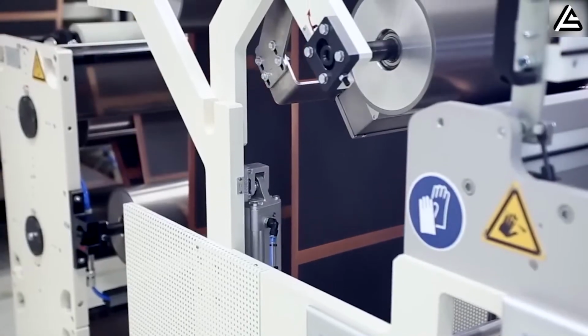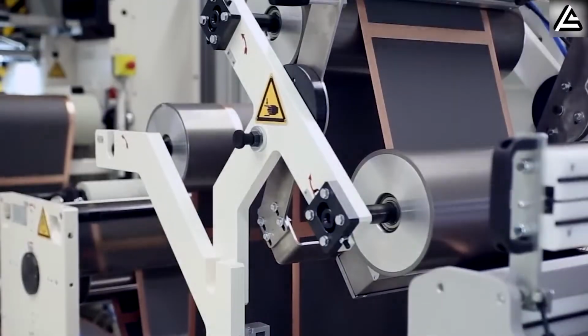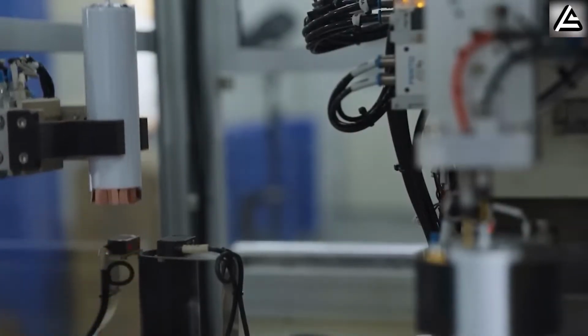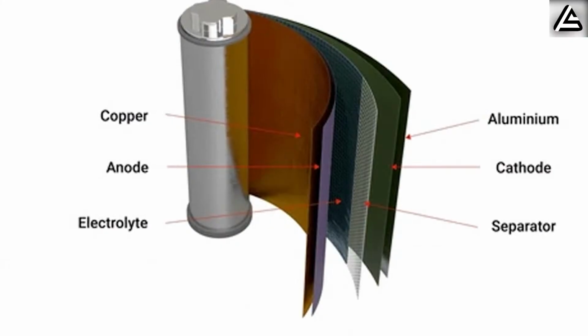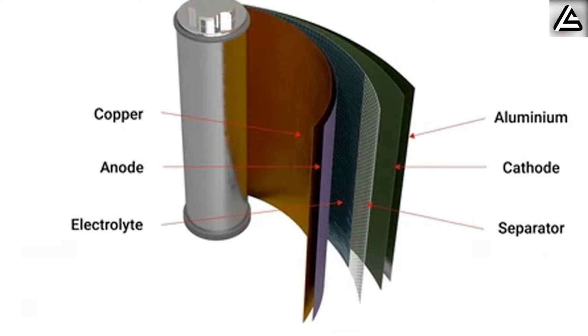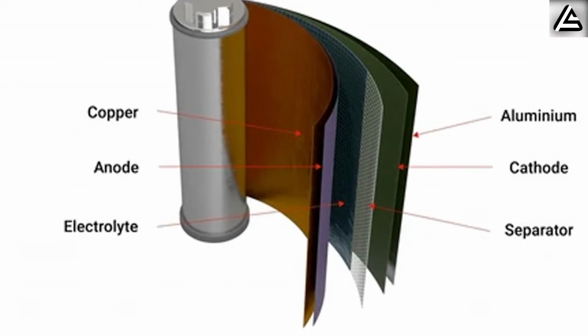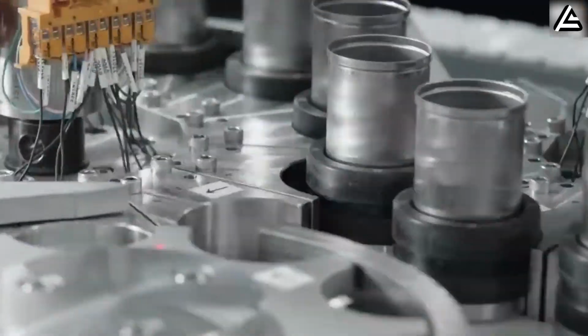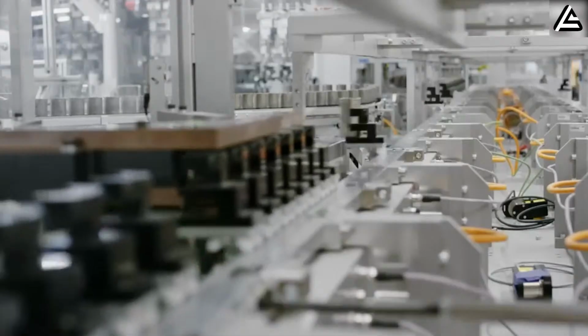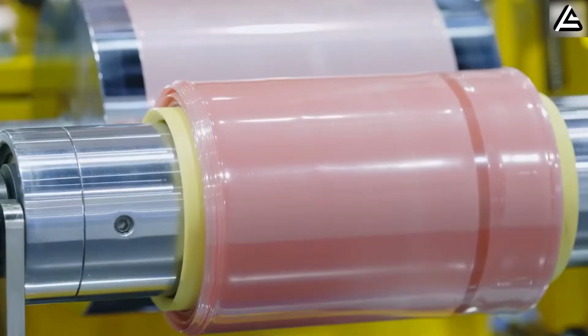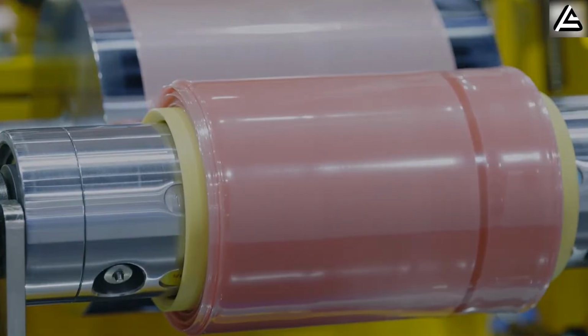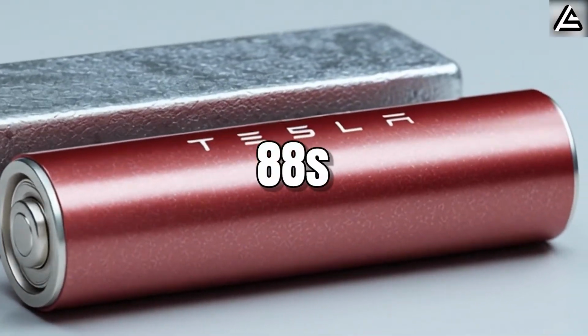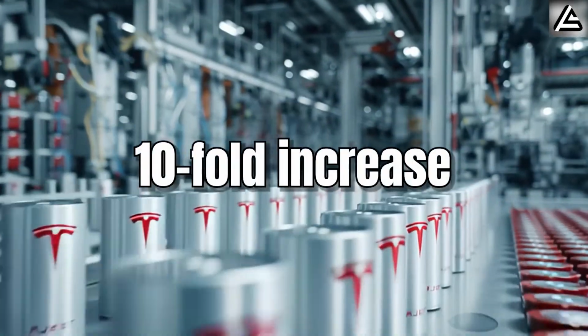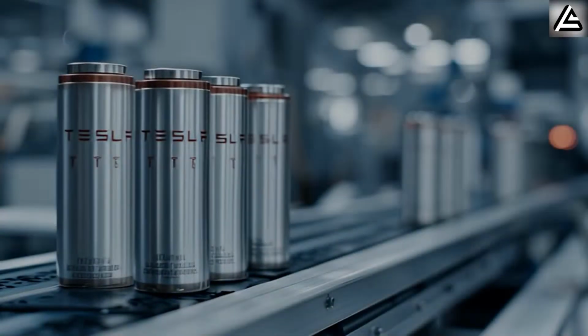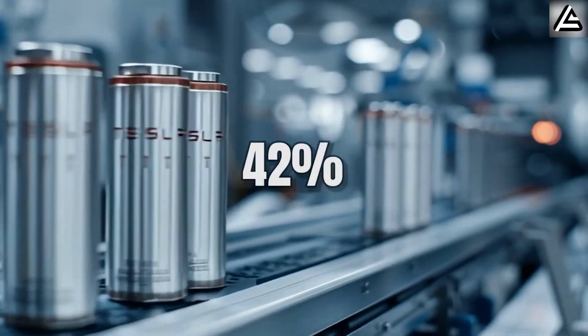Once purified, the aluminum is transformed into high-grade foil and fed directly into Tesla's proprietary roll-to-stack press lines. This advanced line consolidates multiple production stages, including foil stacking, solid-state electrolyte infusion, and electrode lamination, into a single streamlined process. Unlike lithium-ion production, which requires over 180 steps and can take more than 24 hours to complete a single cell, Tesla's method reduces this to fewer than 25 steps and assembles a full cell in just 88 seconds. This translates to over a 10-fold increase in manufacturing throughput and cuts per cell production costs by approximately 42%.